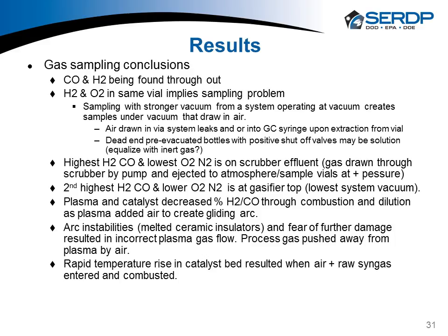Arc instabilities, the melted ceramic insulators, and the fear of further damage resulted in incorrect plasma gas flow, and I think we were pushing the process gas away from the plasma. Anytime we were trying to really open things up, the amperage started going up, the voltage started going down, which is what happened the first time we melted the ceramic insulator. So we were a little gun shy that we were going to destroy the system again, and we didn't really get to understand that well enough at that point in the process.